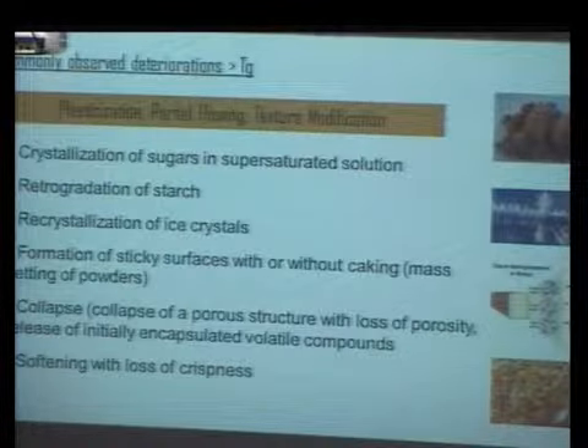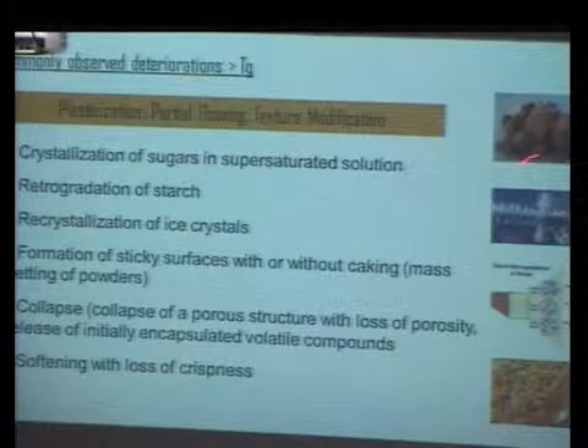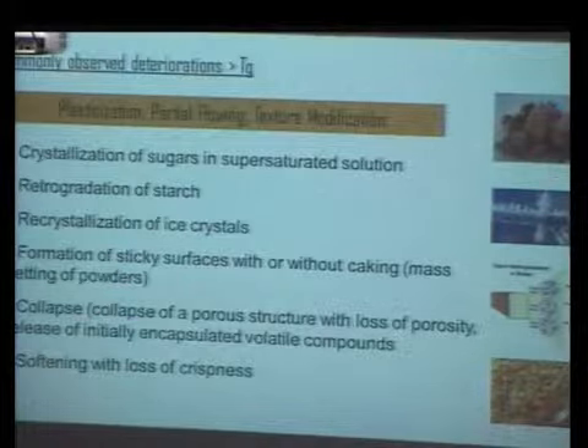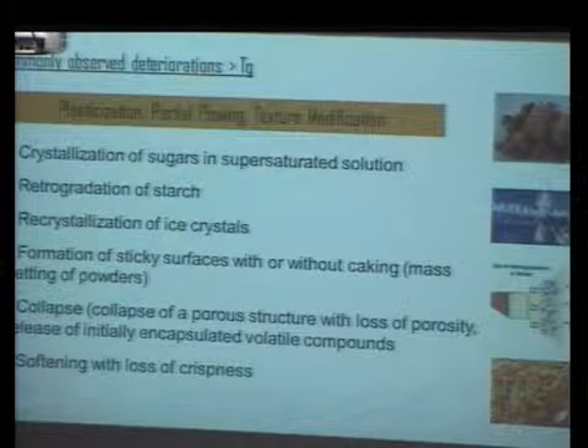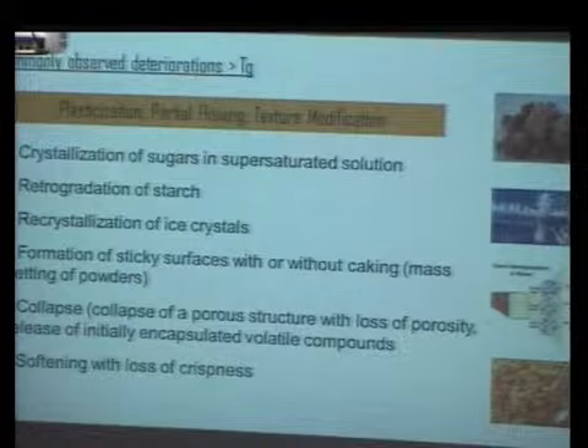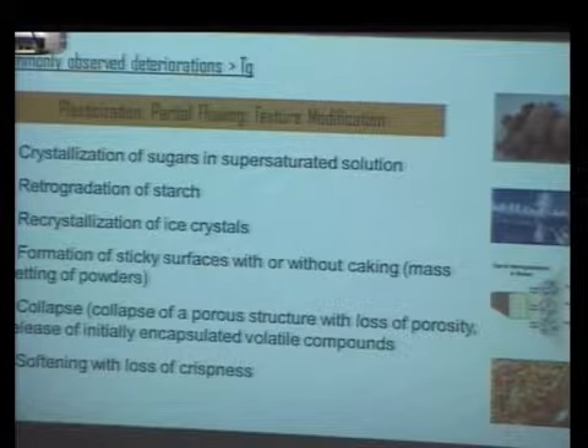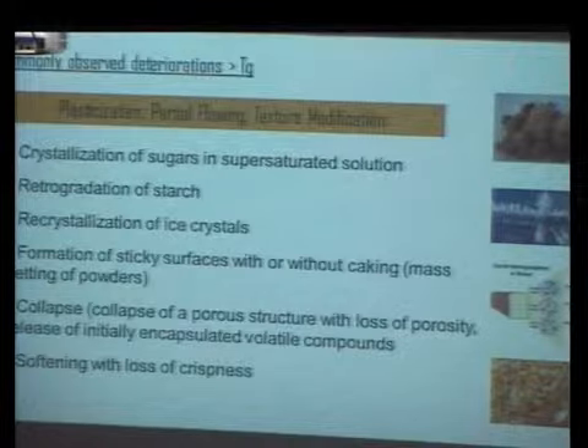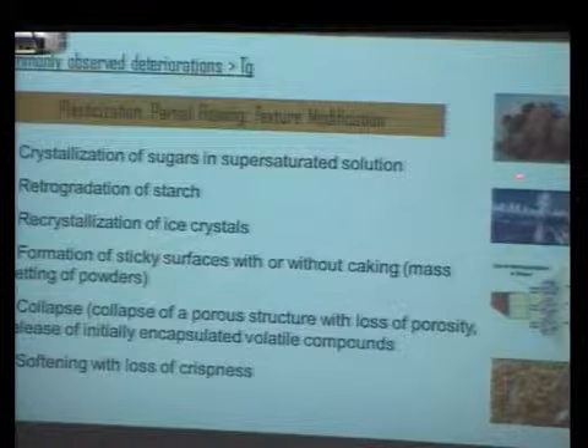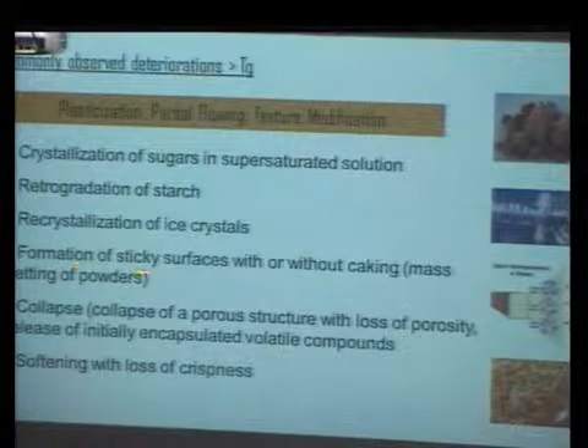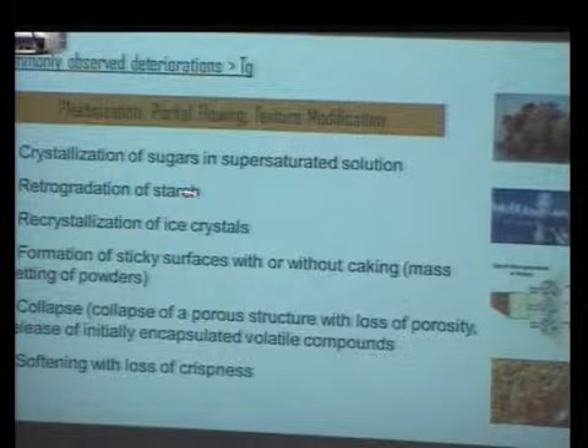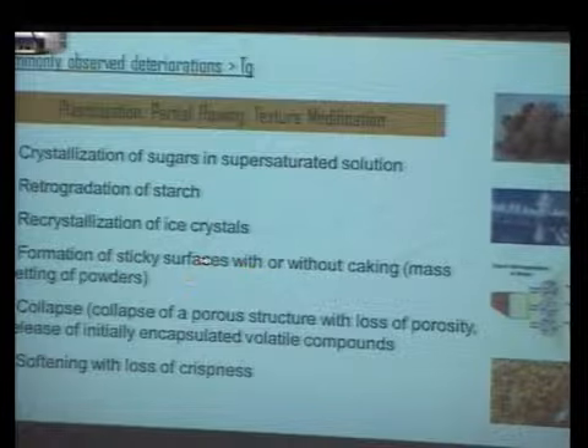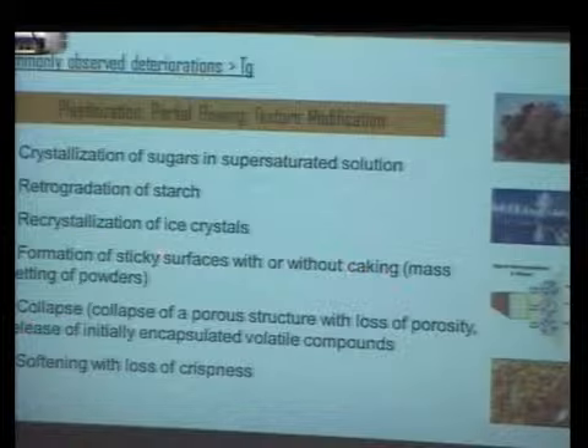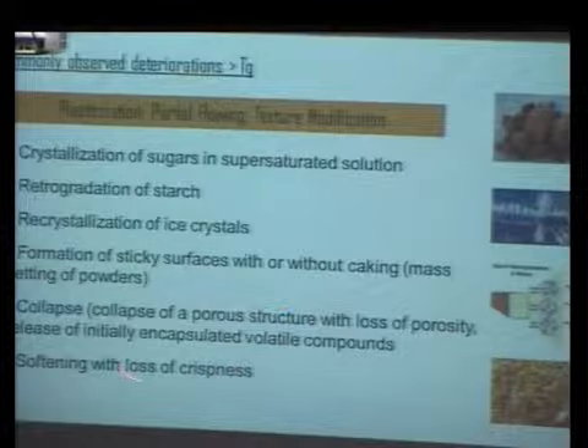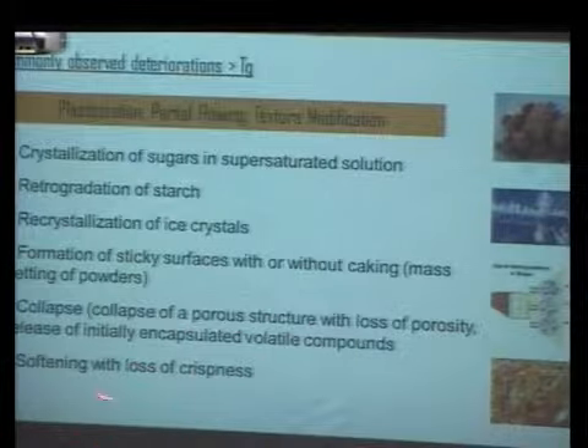And what is the problem in food stability? When you have a powder, you can have a collapse of your powder. For example, when you open a milk powder and you let it stay open, I don't know, one or two weeks or more, and you come back, you see you no longer have a very nice powder. You have some blocks like that. What happened is glass transition. The glass transition of the lactose present in the milk powder gives a sticky surface, since you change the state of your product, with or without caking. You have a collapse, you lose the porosity. You also have the release of volatile compounds, softening, and a loss of crispness.